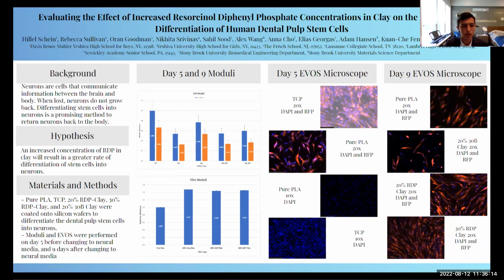The top chart shows the results of the day 5 and 9 moduli, which reflect cell stiffness. As you can see, the cell stiffness decreased between day 5 and day 9, which is a common trend among stem cell differentiation. The bottom chart shows the rigidity of the films. We also compared surface roughness of the films compared to pure PLA.